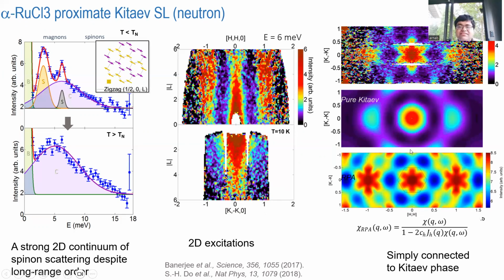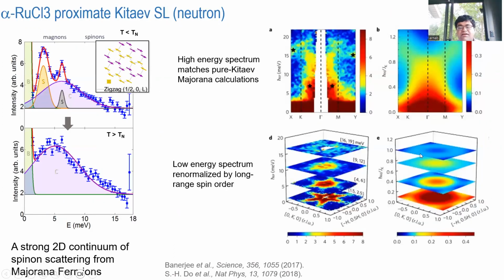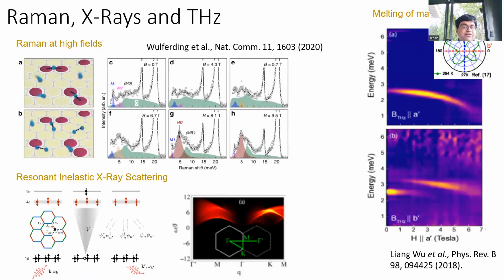But what we found is that if you take this pure Kitaev excitations and you put a little bit of extra interactions in there at the level of a random phase approximation, so you do a little bit of perturbation away from it, you can get to the star-like features that we see in this material. Which means that we are probably simply connected to the Kitaev phase, and we do truly have approximate spin liquid ground states, where there's a high probability that this fermionic continuum that you see is probably coming from just Majorana fermions. So there were other groups who confirmed and also sharpened our claims, which was very nice to see. And there were several measurements that came up using ESR, using Raman spectroscopy, using NMR, terahertz,